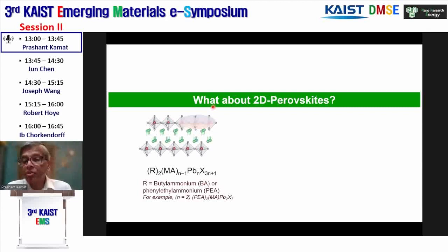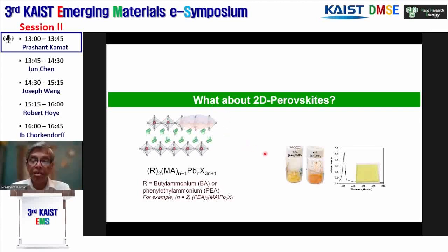So now the question comes, what about 2D perovskites? The 2D perovskites have been recognized as more stable than the 3D. And these are 2D, and you can even crystallize them, this perovskite crystal, just to show you n equal to 1 with butyl ammonium as a spacer cation, and iodide, and you can redissolve it, make films, and characterize them.